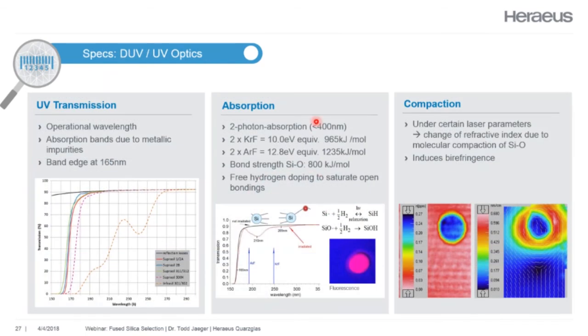Now, if we look at some of the specs here, once again, the transmission and absorption are important, just as they were with the infrared. And then there's a third item called compaction that I'll briefly cover. For the UV transmission, you really want to consider what wavelength you're operating at. If you're at 193, you can see that infrasil is probably not going to be the material of choice. The absorption bands that you're seeing in the infrasil are really due to metallic impurities in the fused quartz process. So you want to avoid that.